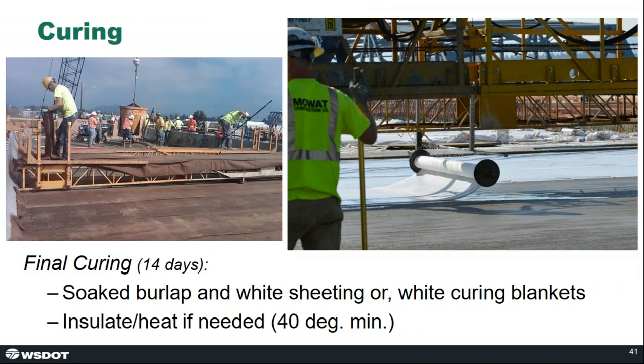Then after final set, we move to our final curing system. And as I mentioned, we've increased this to a 14-day cure. We typically apply soaked burlap with white sheeting on the bridge deck. The soaked burlap maintains moisture on the top surface of the concrete to prevent any evaporation. And the white sheeting serves to reflect some of the solar heating.